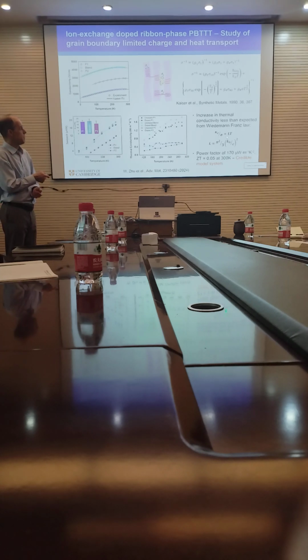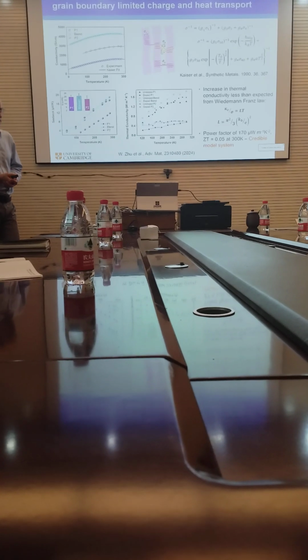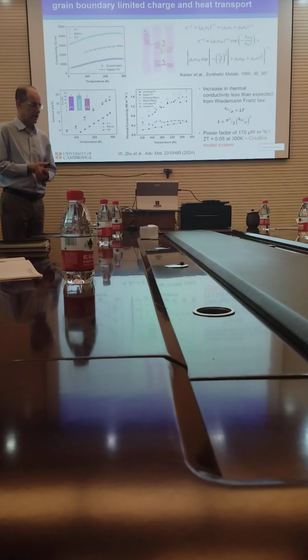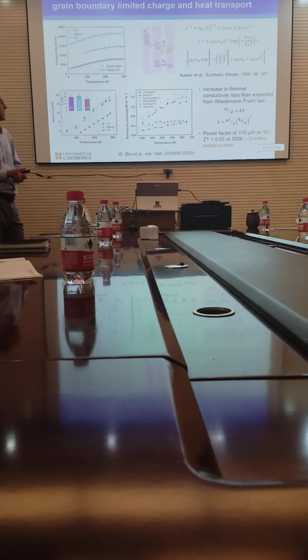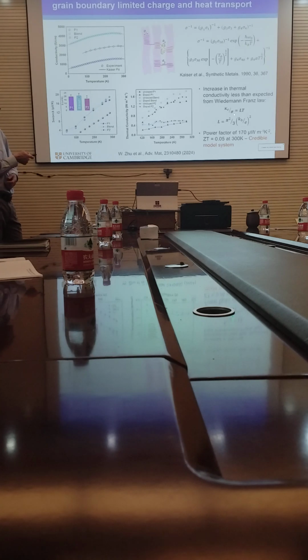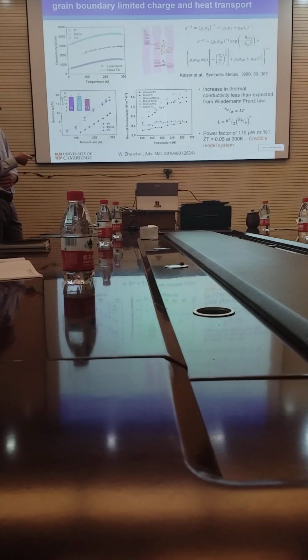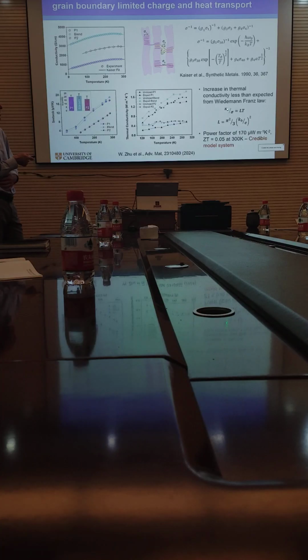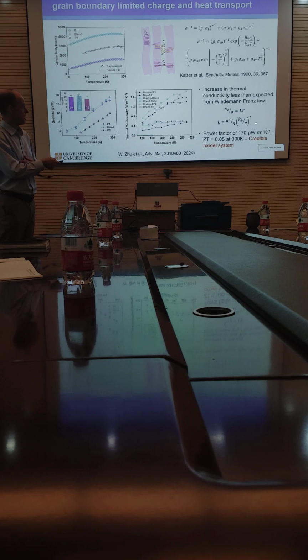There is actually a law that tells you how much the thermal conductivity should increase when you dope. So there's the so-called Wiedemann-Franz law that describes the ratio between the electronic contribution to the thermal conductivity, kappa E, over the electrical conductivity sigma, which should be given by a fundamental constant, the so-called Lorentz number, which you can express in terms of the Boltzmann constant divided by the electron charge, and then times the temperature.